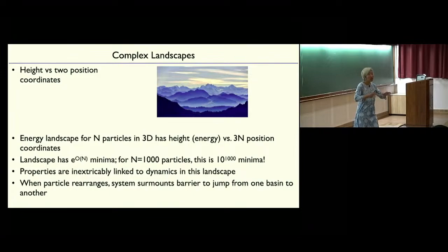People have been able to map it out numerically for maybe up to 60, 80 particles now, but that's about as much as you can do. The problem with this is that the properties that you see completely depend on how you explore this landscape. All right. And rearranging a particle requires the system to jump over an energy barrier. So it's going over a barrier in this landscape from one basin to another.